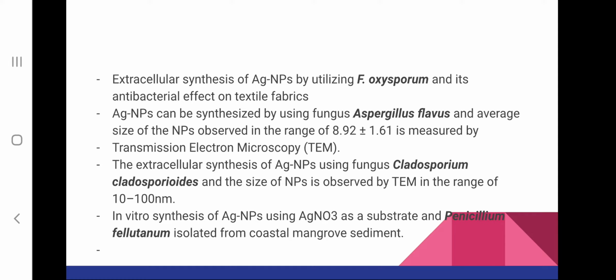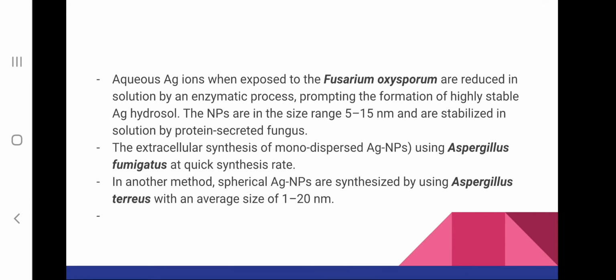And Cladosporium cladosporioides is also utilized for synthesizing silver nanoparticles extracellularly, and also using Penicillium fellutanum, which is a fungus that has been isolated from coastal mangrove sediments, silver nanoparticles can be synthesized using silver nitrate solution. Then Fusarium oxysporum can synthesize nanoparticles of 5 to 15 nanometer size.